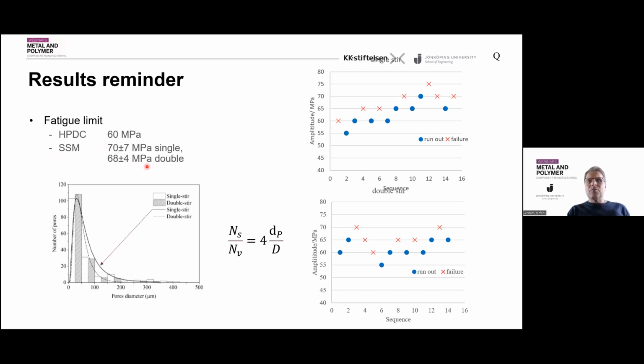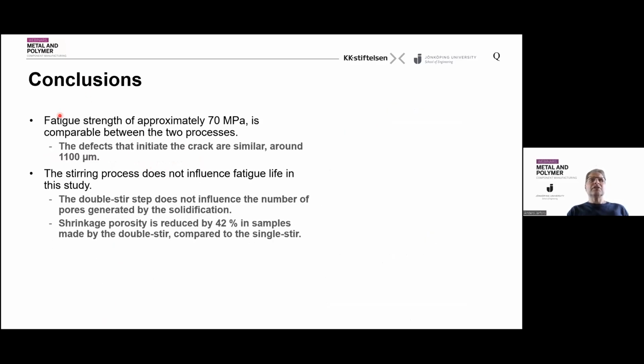When you focus on this, what we can say here is that the fatigue strength was approximately 70 megapascals and was comparable between the two processes. Now, what we could see is that defects initiated in similar locations, and there were cracks with crack sizes about 1100 micrometers. And in the stirring process, since this did not significantly influence the fatigue life in this, we could say that the double stir process did not influence the number of pores.